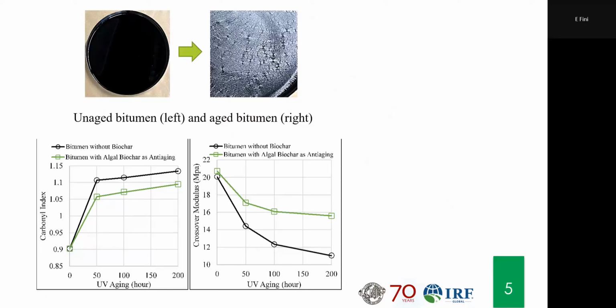Initially, you see a big jump, and then the increasing rate will be slower, but you still keep seeing them going up. We only went up to 200 hours, which was still pretty severe, and we stopped right there. You can see how it goes up. And then we looked at mechanical indicators. As I mentioned, one indicator is just my eye looking at it. Another indicator here is a chemical indicator based on FTIR, and the mechanical indicator is based on crossover modulus.